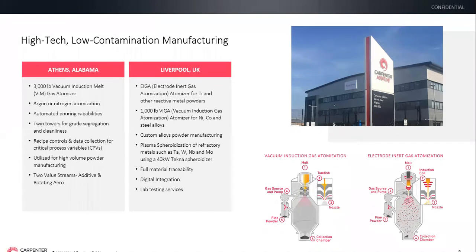In Alabama, we have a 3,000 pound atomizer. We are able to perform argon or nitrogen-based atomization as the gas source. This atomizer has automated pouring capabilities. It has twin towers, so you can clean out one while you are segregating the powder that you produce in the other tower.